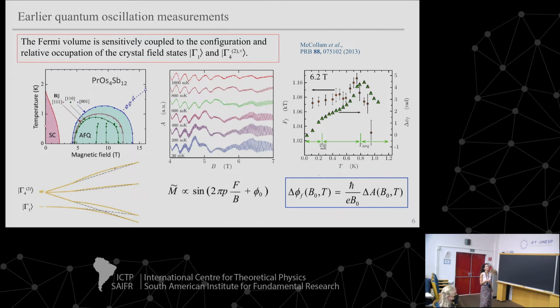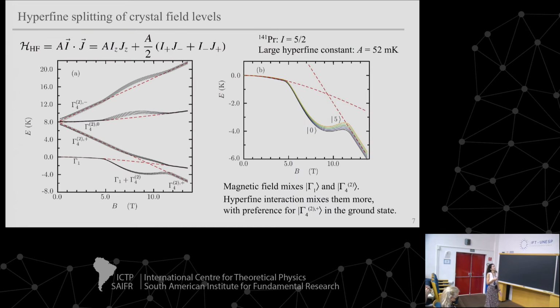So even at this stage, we looked into this, and then we thought, okay, we're neglecting to think about hyperfine interactions and the nuclear degrees of freedom. So we put this into our Hamiltonian. This is just a hyperfine term that we added to the mean field Hamiltonian. And our level scheme then looked like this. These are the triplet and singlet levels. Magnetic field will split them and mix them.